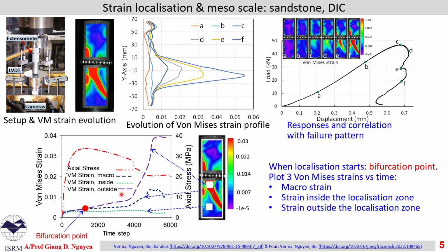If we plot the evolution of strength, say axial stress and time, together with three different strains: the strain inside the shear band, the red zone here, the strain outside the shear band, and the macro average strain, we clearly see the bifurcation point, beyond which all these three strains follow different paths. Outside the shear band, unloading happens. As you can see, there is a reduction of strain outside the shear band, while the von Mises strain inside the shear band keeps increasing. The macro one is the volume average over the surface here.